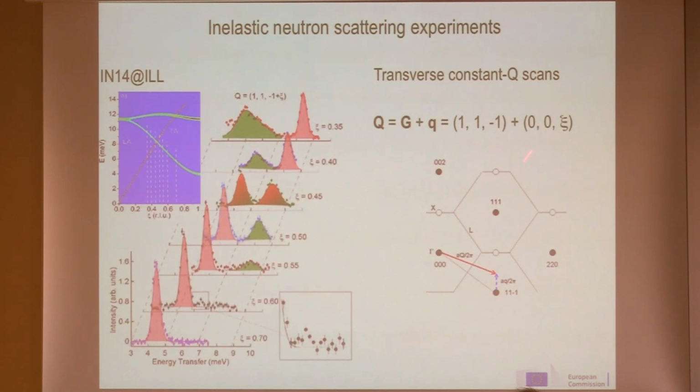How can we observe this? For instance, these are inelastic neutron scattering measurements without polarization analysis. We have scanned along these lines, from 0.8 to 0.2, so the crossing will be here at 0.45, 0.5. You see that here we see just the magnetic excitations. Here we start to see the phonons. Then at the crossing position, you would expect only one peak at this energy. And instead, you see that there is a splitting remaining. It's the avoided crossing and so on. Then they swap the interaction. Here now is the phonon, and this is the magnetic.